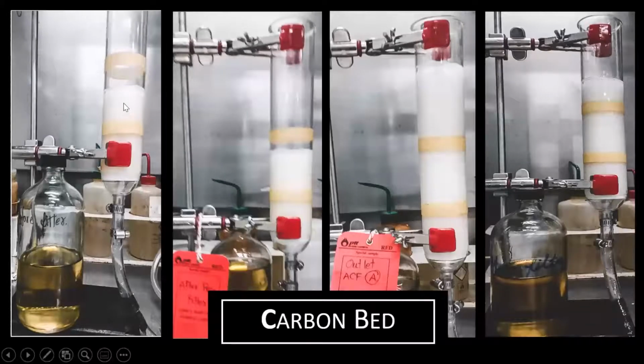This is lean amine feeding the filters. This is the lean amine after the pre-filter, and you can see it's about the same foaming tendency. And this is after the carbon bed. The amine foamed worse after the carbon than it did before. That's not what should happen.